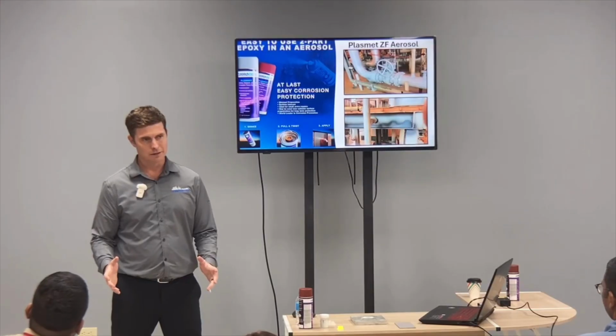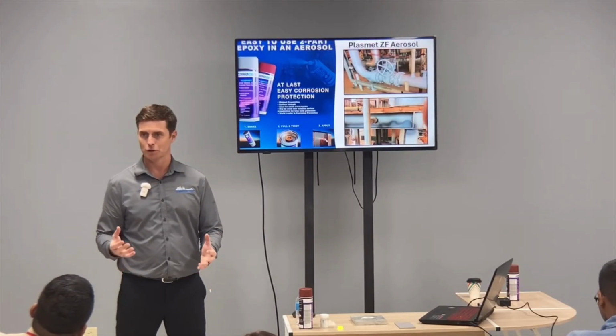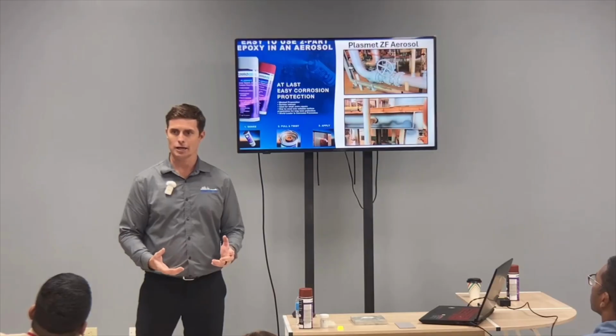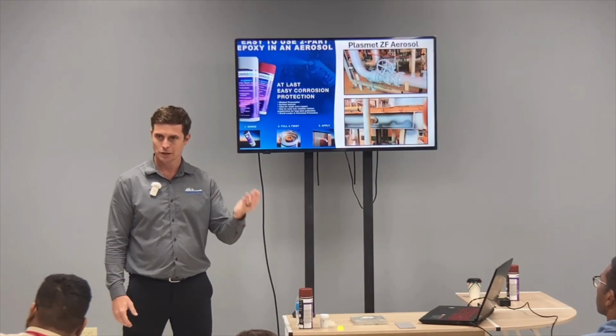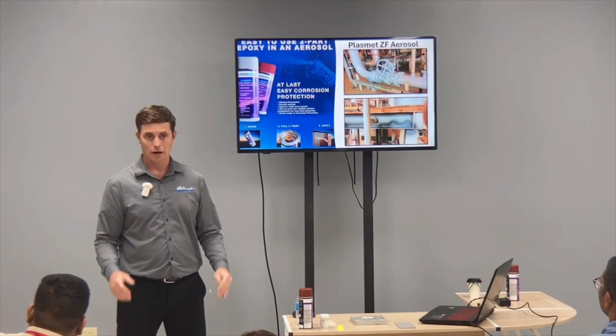The downfall is improper training. So what we've done is we've created a user guide so that you can classify the severity of the corrosion into multiple different levels. If it's more severe, you might use a backpack and use a bristle blaster and power tools. We've even created small little 8-ounce kits of Chlor*Rid, which reduce the chlorides. But you take that corrosion deposit off, you either do one coat to get about 7 mils DFT. That'll get you, in offshore environments, about a year. That's enough to deal with it before you go back and blast and paint the block.